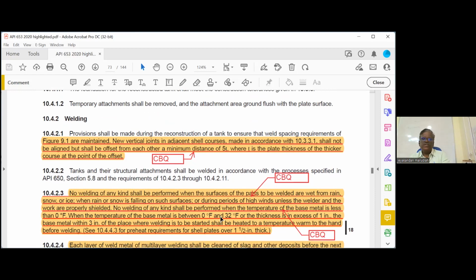When the temperature of the base metal is 0 to 32, the thickness of excess in 1 inch, the base metal in 3 inch shall be started to be heated to the temperature warm to the hand. This requirement is also not in 650. So we are comparing construction and reconstruction. These are special requirements for the reconstruction.